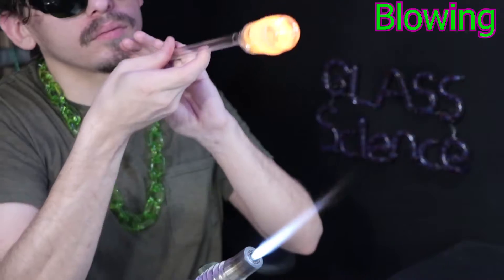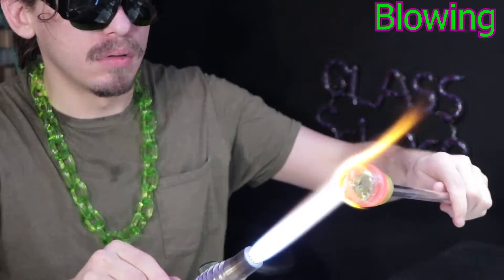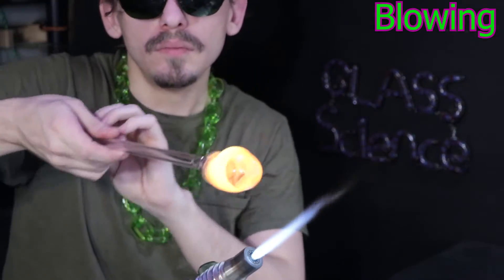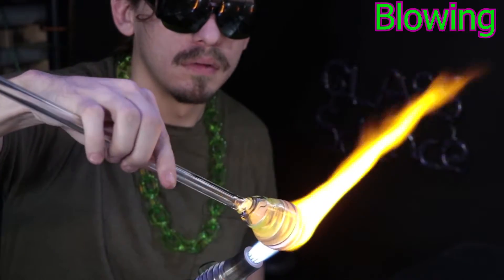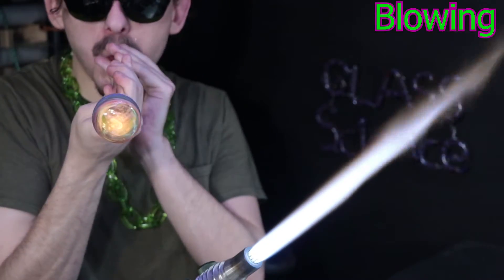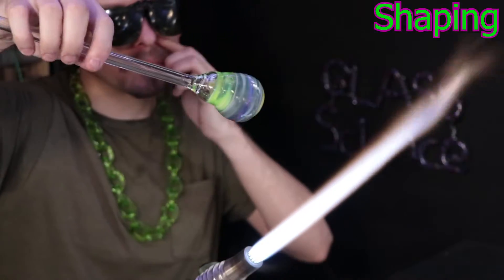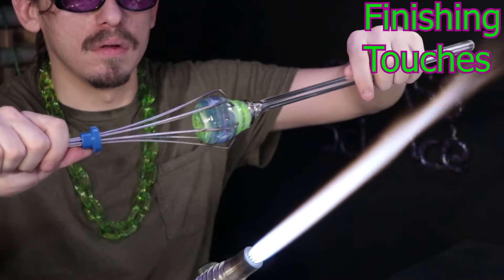As you go to blow the sphere, the thicker areas will hold heat longer and expand further, while the thinner walls will lose heat quicker and solidify faster. So naturally the glass will just even out its thickness through that heating and blowing process. In the next video, I'm going to demonstrate the technique called the solid color blowout — instead of making the tube like I did, I'll just melt a big glob of glass and blow that out into a sphere.